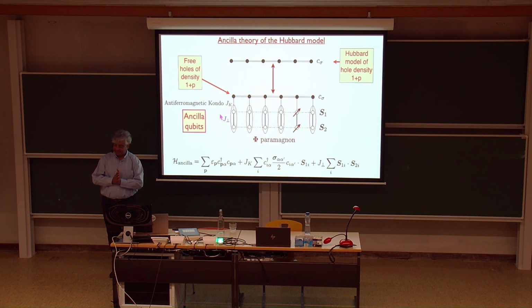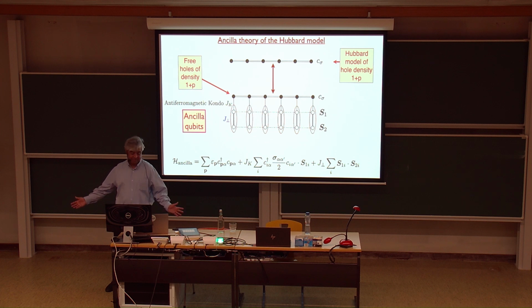Okay, so my claim is I can rewrite the single band Hubbard model as some kind of Kondo model, but not with 1 layer of spins, but 2 layers of spins. And they have to be spins that can form a trivial ground state, which they can, they form the singlet state, but then the top layer would just form a Fermi liquid of the hole density P.